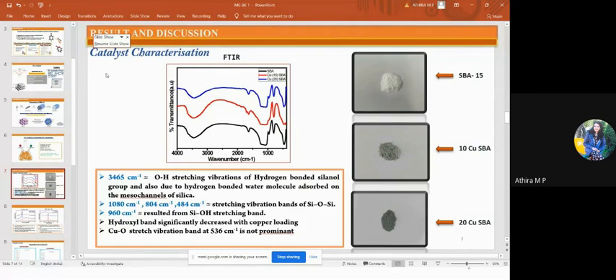The bands at 1080, 804, and 484 cm⁻¹ are stretching vibration bands of the silicon-oxygen-silicon bond, and the band that appeared at 960 cm⁻¹ results from the silicon hydroxyl bond. The copper oxide stretching vibration band at 536 cm⁻¹ is not that prominent, and the result demonstrated that a significant amount of copper is successfully incorporated into the framework of SBA-15.